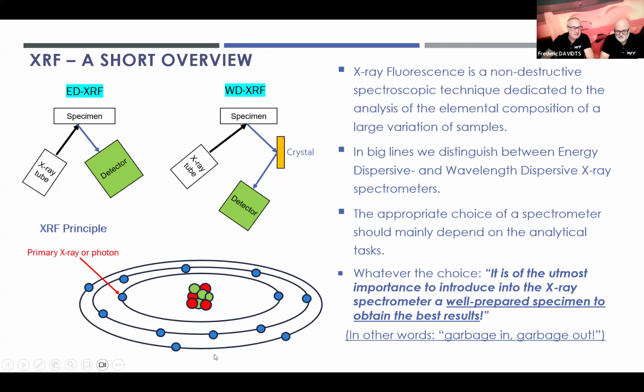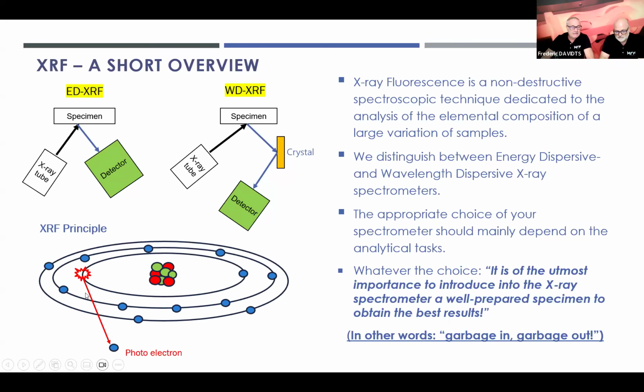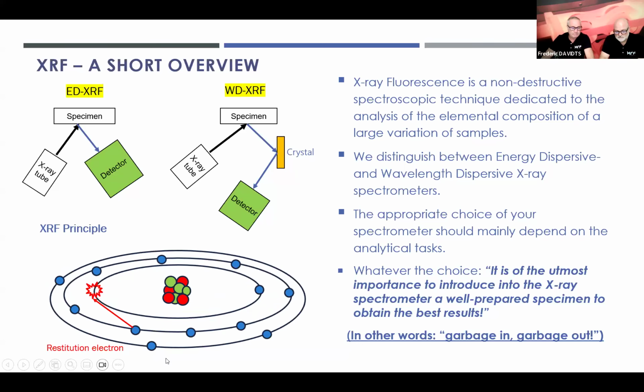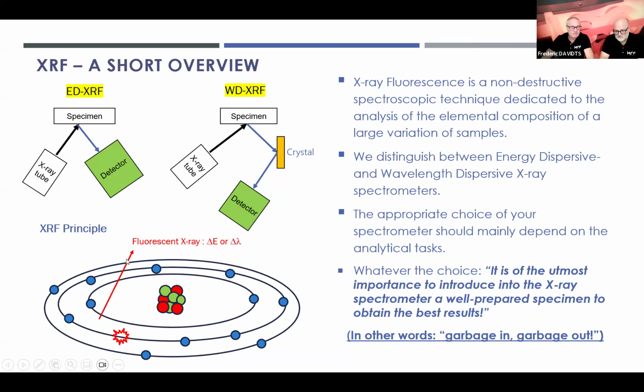We have a sample that contains a huge amount of atoms, and I represent just one atom here, which is in our specimen. So by means of an X-ray tube, we will shoot primary X-ray photons onto our specimen, and the inner electrons may be excited, forming a photoelectron. Now this atom is going to try to stabilize itself again, and external electrons will drop into this vacancy, and the difference in energy between the inner electron and the outer electron is really what we are going to analyze as fluorescent X-ray, let it be energy or wavelengths.